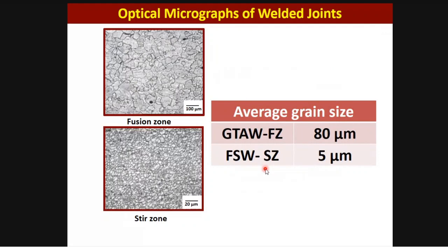And then this is very important, fusion zone. In the TIG welding, we used to say it is a fusion zone because it's an autogenous welding without filler metal addition. We welded a 4 mm thickness only, without filler metal addition here in the TIG welding, GTAW. And this is the friction stir welded IF steel joint stir zone.